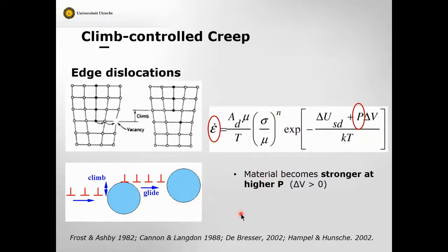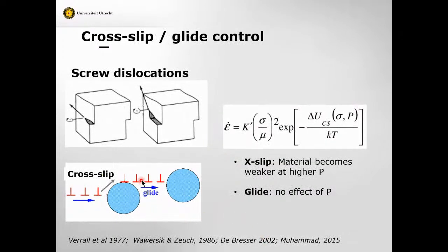It can also be controlled by another process called cross slip. When you have screw dislocations as the dominant type of microscale phenomenon going on in the crystal, they don't climb, they can slip into different glide planes. And if indeed this process of jumping onto different glide planes controls the rate of movement of dislocations, you can also derive microphysical laws for this, based on the dynamics of motion of dislocations under stress.